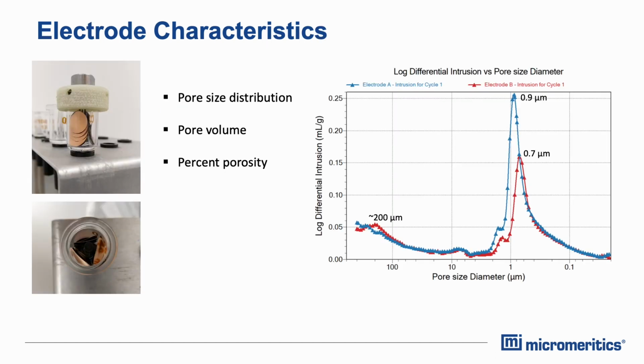On this slide, I brought you one example where two different electrodes, which should have a similar performance, were tested and compared to each other. The graph that we see here is the pore size distribution. We see the intruded volume as log differential intrusion versus the pore size. For this material, we see that there are some larger pores in the range of 200 micrometers, and in this range, both materials behave quite similar to each other. Then we see a main peak for both materials. For electrode A, it's with the maximum at 0.9 micrometers, whereas electrode B shows the maximum at only 0.7 micrometers. So the materials are comparable, similar to each other, but still show some differences.